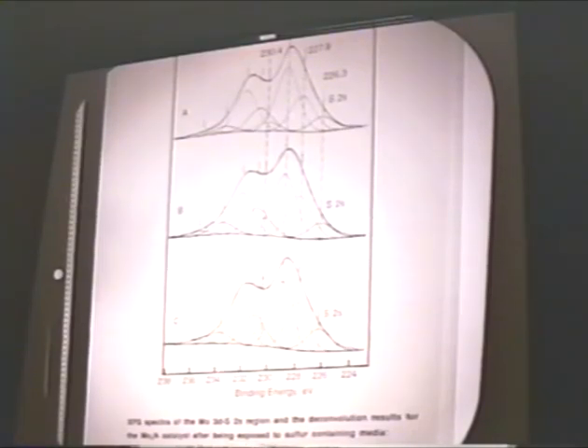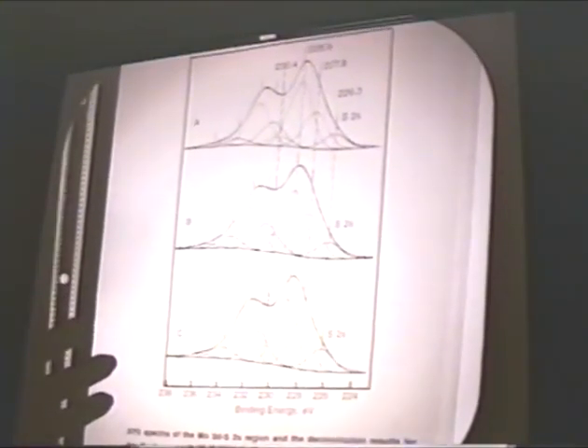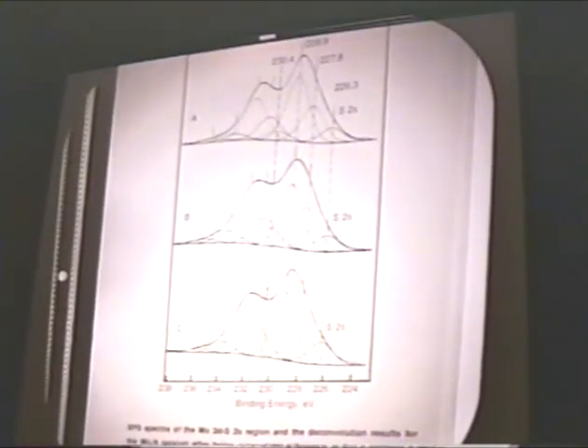And HDS in the presence of ammonia. Again, the tracing lines are a little maybe weak to see, but in every case we see the original three peaks that correspond to the molybdenum signal that we have seen. Now there is also here